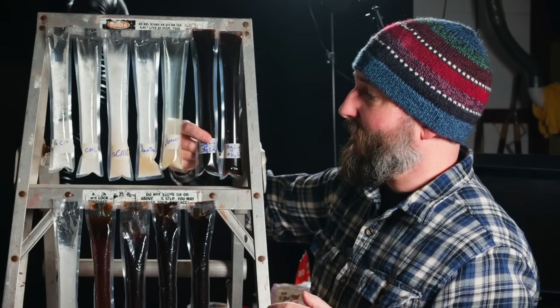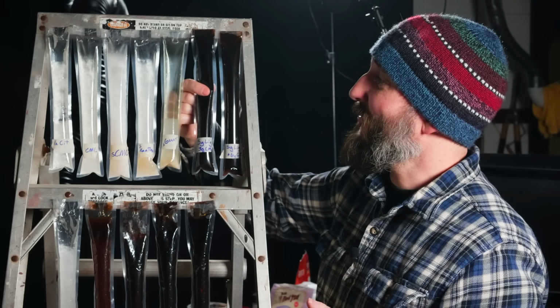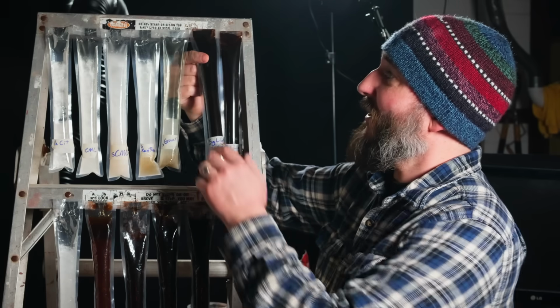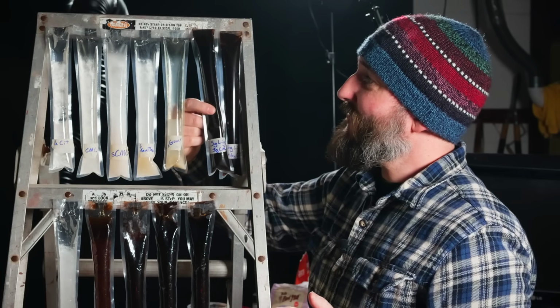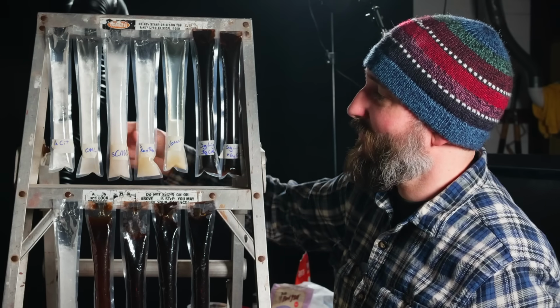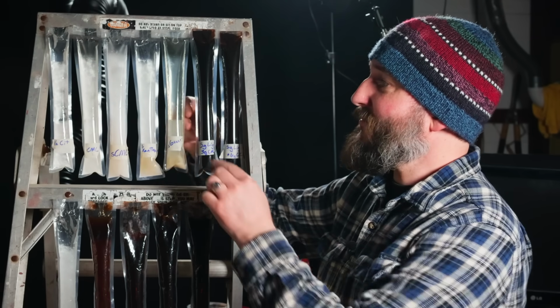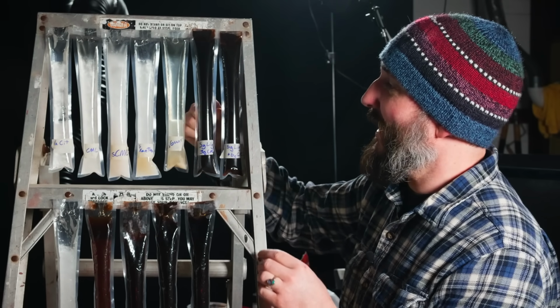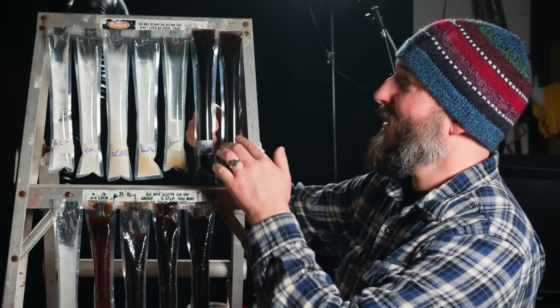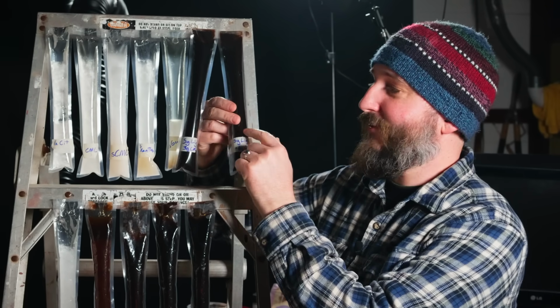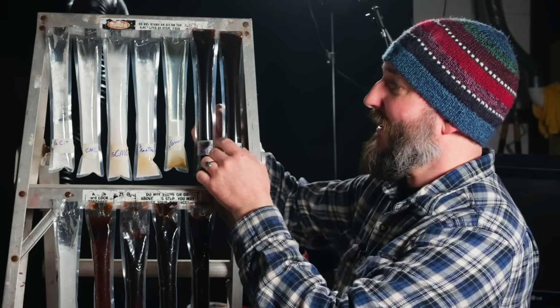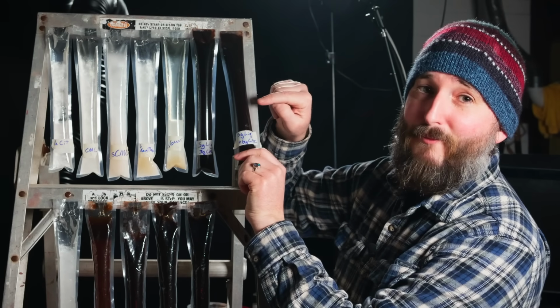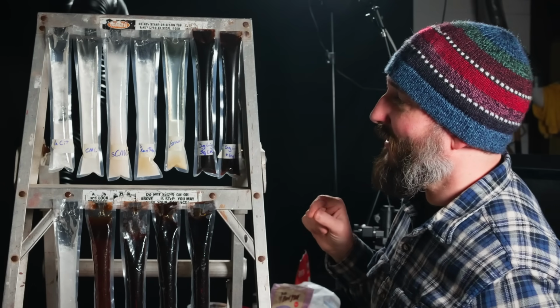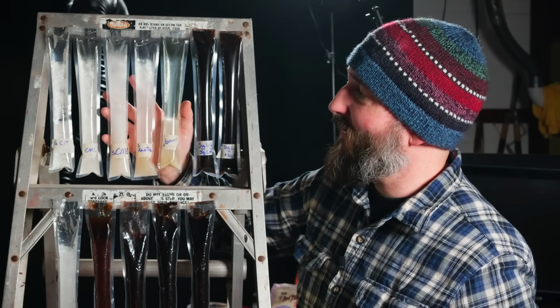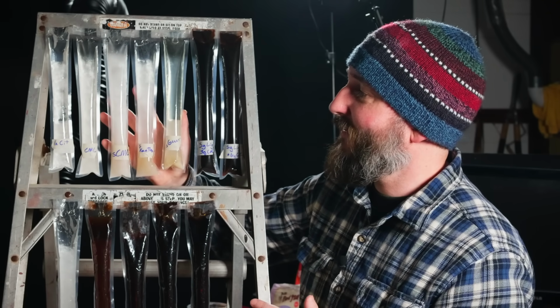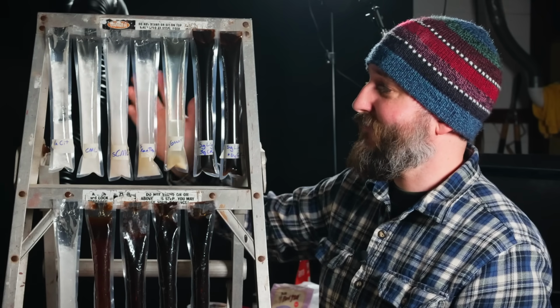So this is a stabilized lignosulfonate sample that froze really well. It's really homogeneous, hardly any liquid at the top, and I can't feel any hard crystals. And this is a better result than the standard CMC, and so something has improved about this. I really am curious to see how this one is going to hold up after repeated cycles. And for this one, I've just doubled the amount of CMC. So this is actually thicker than any of the other tests. I can't really compare it directly to them, but if this is the top performer after repeated thermal cycles, it'll just tell me that any of the flaws in these three up here of my sulfonated samples could be corrected by just adding more of the thickening CMC ingredient.